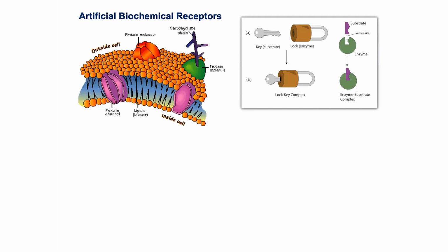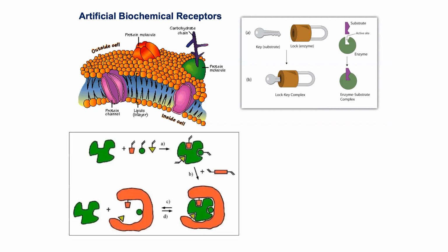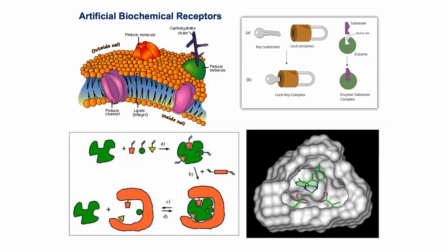The key, or the substrate, is very specific for that lock or enzyme, and therefore action can be induced by the presence of these highly specific interactions. So a well-known approach called molecular imprinting polymerization takes advantage of the interaction between monomers for vinyl polymerization and the analyte or substrate. Subsequent cross-linking results in cavities that are very specific for the original template, as shown here, which means you have very high binding constants for assay studies.